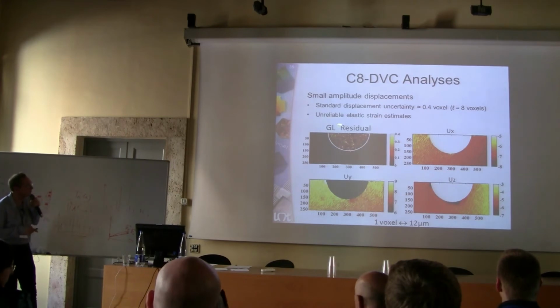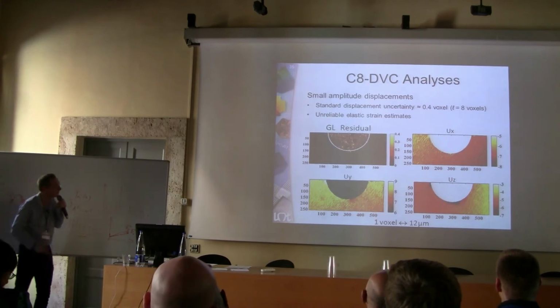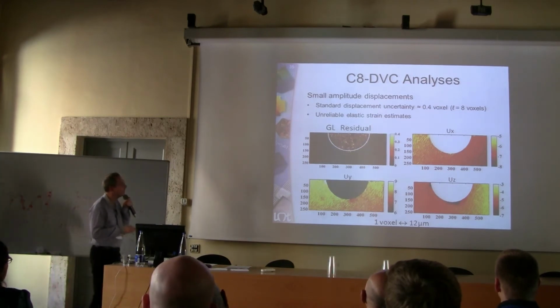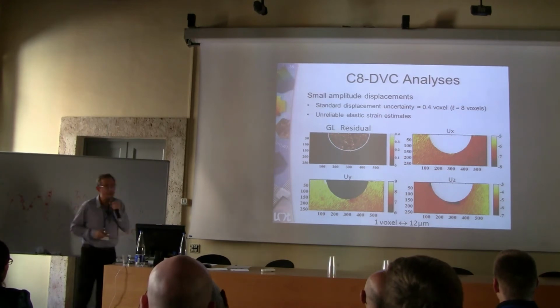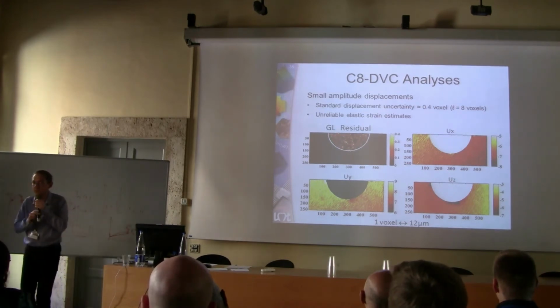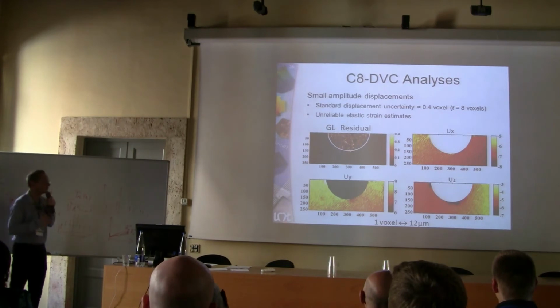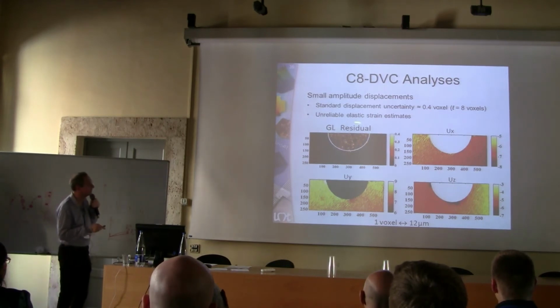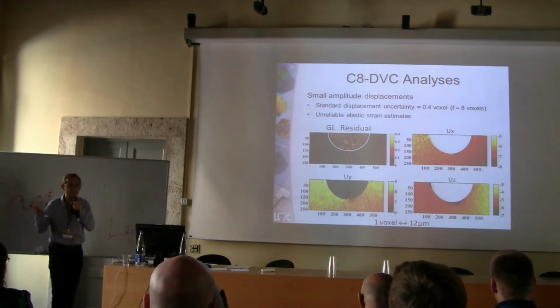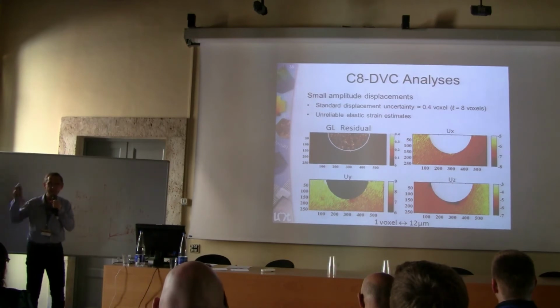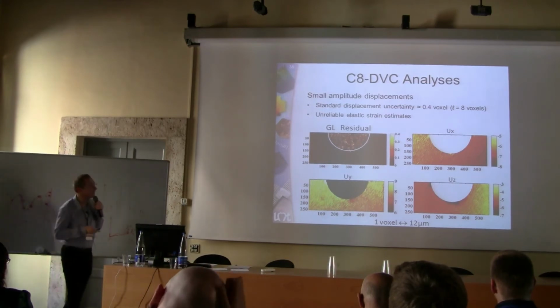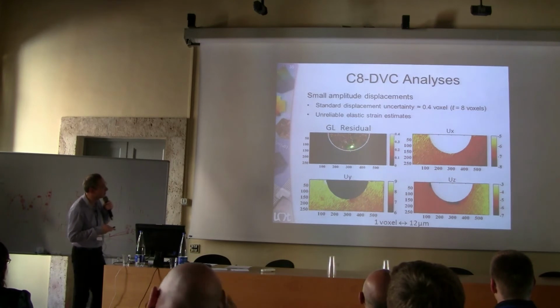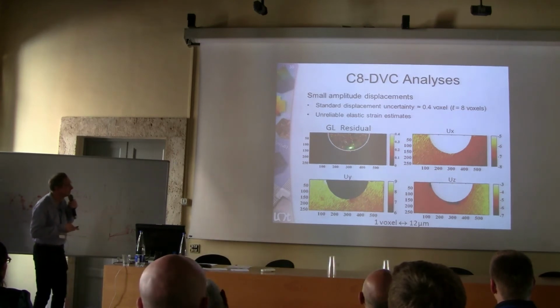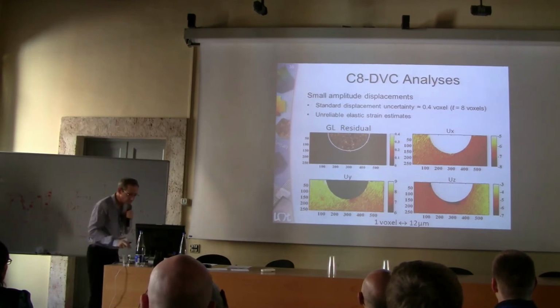But we would still want a very good description of this front. Now note also that because we have this crushing zone, the residuals tell us where the calculation didn't work, and basically it was in the crush zone because we don't have conservation of gray levels due to this pore collapse. So in that sense, DVC is doing its job, but it's still difficult to extract meaningful information.